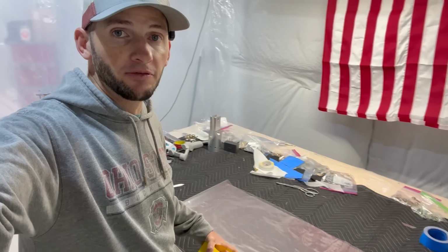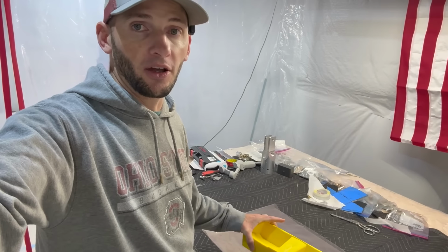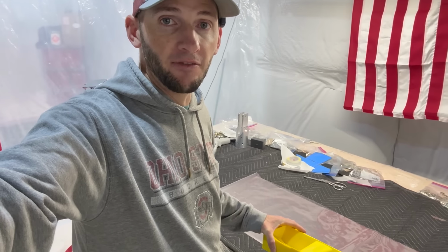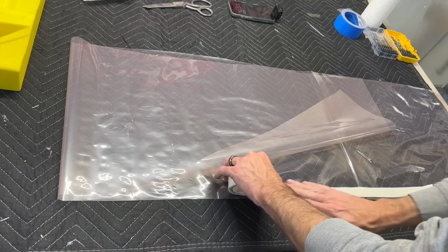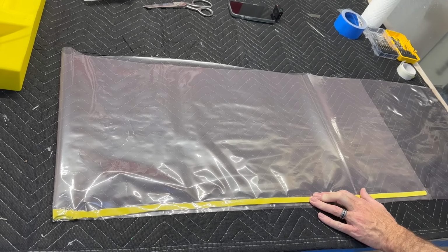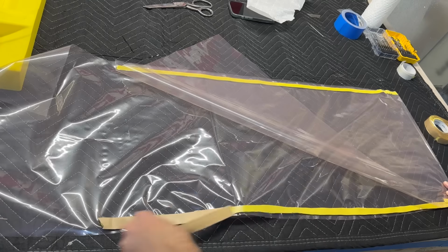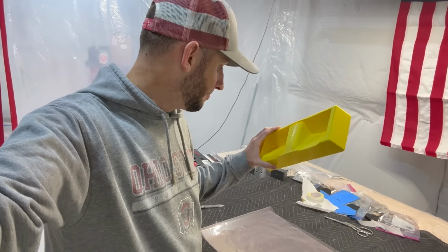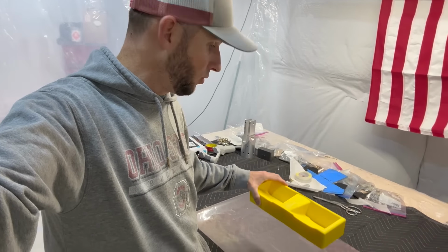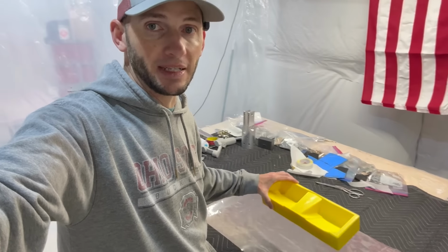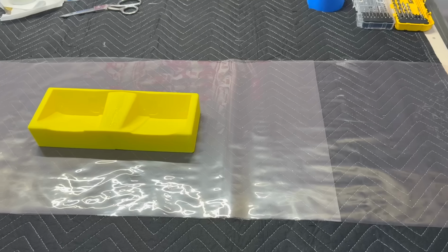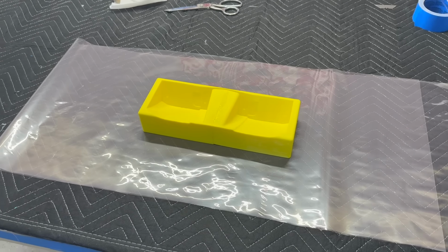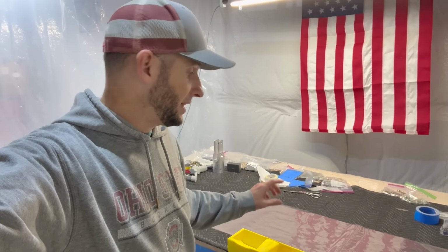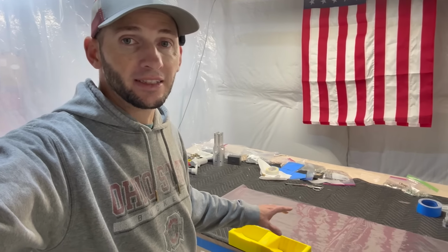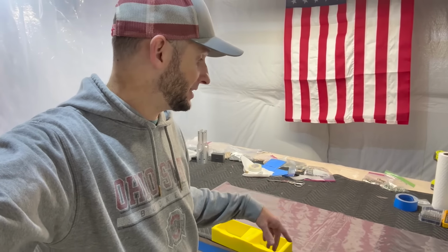Now, unlike resin infusions where you put the vacuum bag directly on the mold surface, we're going to be creating an envelope bag, which is exactly what it sounds like. You're going to put the entire mold and part all the way into the bag and vacuum bag the entire thing. Now, one important thing to note here is you want your envelope bag to be at least 2 to 3 times bigger than your mold. Too much vacuum bag is always better than too little. The reason you're doing that now is so that you have one less thing to screw around with while the resin is in your part curing and you need to get it under vacuum.